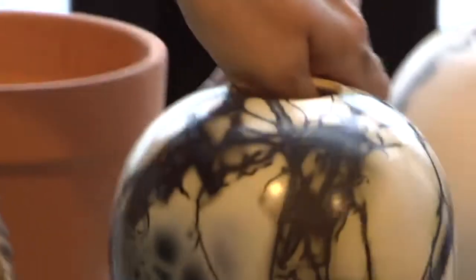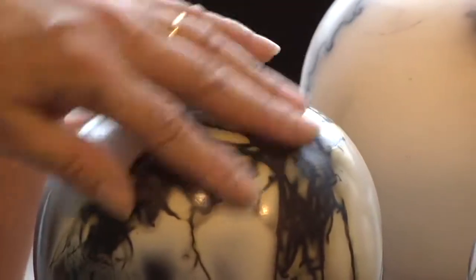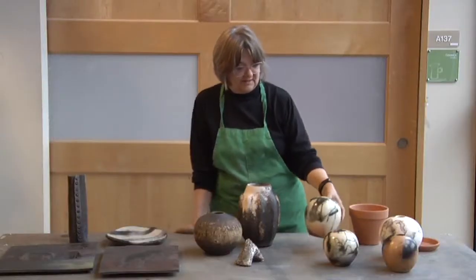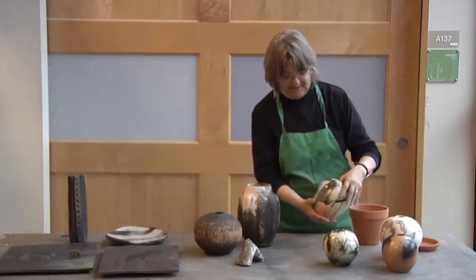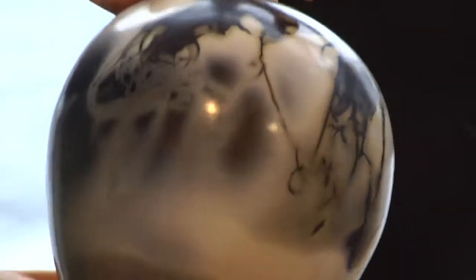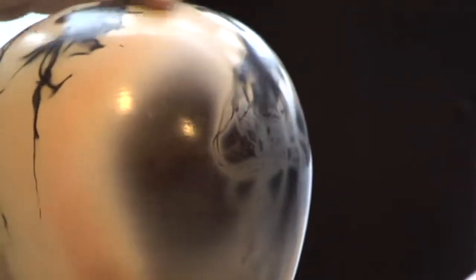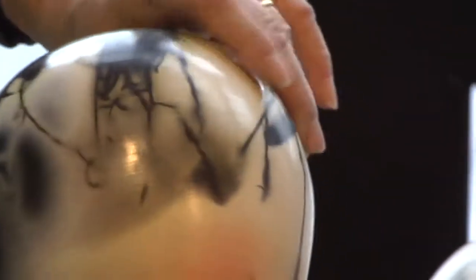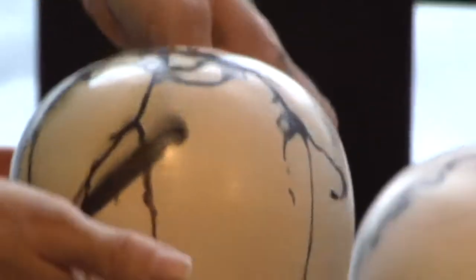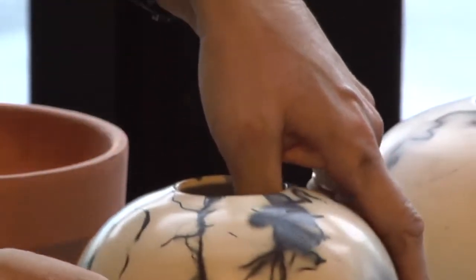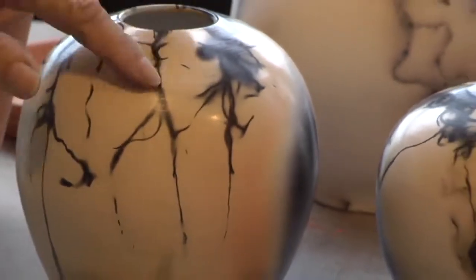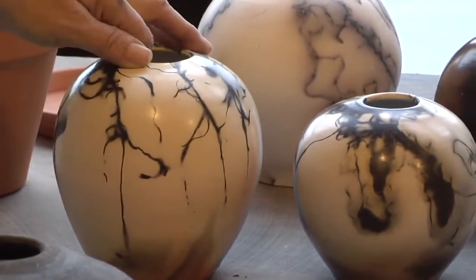This is waxed after it's cleaned up. If you want to wash it first, let it sit for a day so it's dry before you put the wax on, because it'll get gummy. So you just want to buff it on with a shoe polish brush, or they come with applicators now, and then buff it with a piece of soft cloth like a t-shirt or a silk Hawaiian shirt or whatever you have around. And so that'll seal it and make it a little bit more durable so it doesn't scratch, because it is a delicate surface.